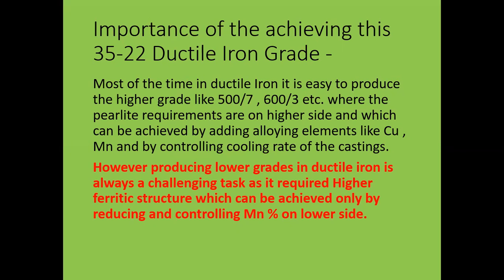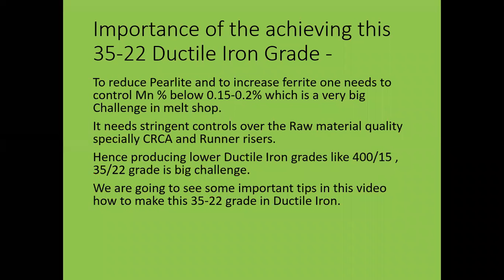However, producing lower grades in ductile iron is always a challenging task as it requires a higher ferritic structure, which can be achieved only by reducing and controlling manganese percent on the lower side. So producing lower grade in ductile iron is a great challenge and needs stringent process control. To reduce pearlite and to increase ferrite, one has to control manganese percentage below 0.15 to 0.2%, which is a very big challenge in the melt shop.